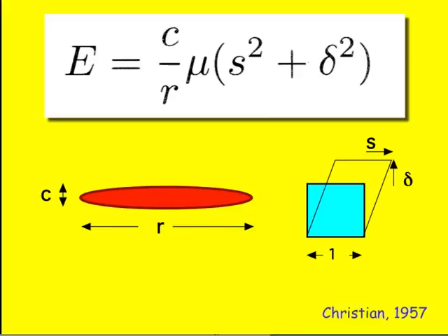So this is also the reason why mechanical twins are extremely thin, because the shear deformation for mechanical twins is even larger than for martensite. It's 0.7071, yeah, 1 over square root of 2 for mechanical twins. So they will form as extremely thin plates with very sharp tips, in contrast to annealing twins, which do not involve any deformation, so they form as blocky things which minimize the interfacial energy. Okay? So anything which involves a shear deformation and a volume change normal to that habit plane will form as thin plates, because these are massive deformations compared with ordinary elastic strains.